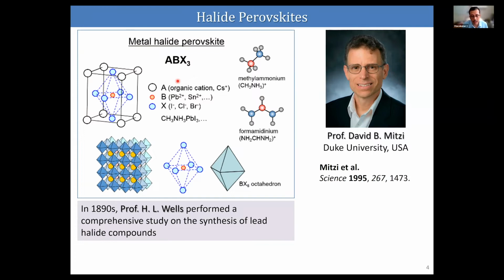In the perovskite oxide, the cavity is occupied by another metal ion, but here it is mostly organic cations. We don't have many choices because the cavity is really small, so you can use only small cations like methylammonium or formamidinium. But of course, if you want to make an all-inorganic halide perovskite, there is a possibility of using cesium. Its ionic radius is very suitable for the cavity generated by these octahedra. So these three cations can generally be used to produce three-dimensional ABX3-type halide perovskites.